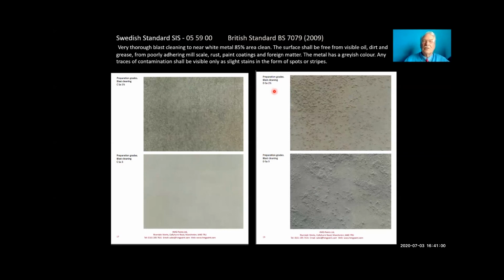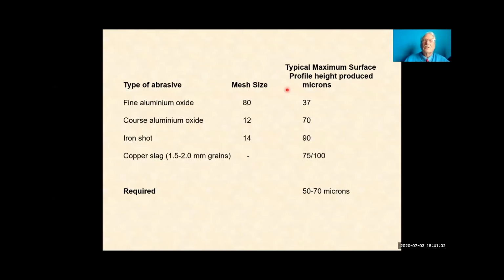And the sort of abrasive you're looking for is these sort of mesh sizes. So this is holes per inch in the sieve mesh for the grit. And we're trying to get, if you remember, between 50 and 70 microns peak to peak distance on our roughness. So the roughness peak to peak should be about 50 to 70 microns.